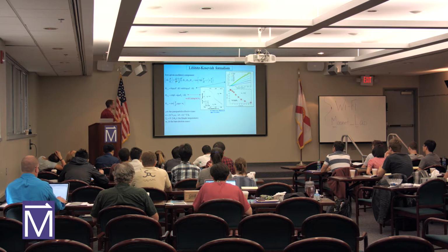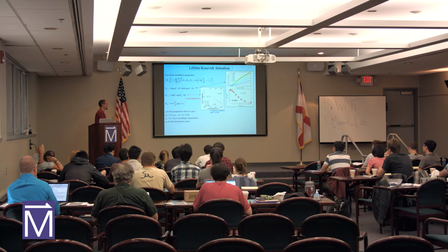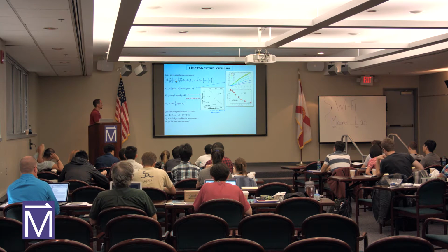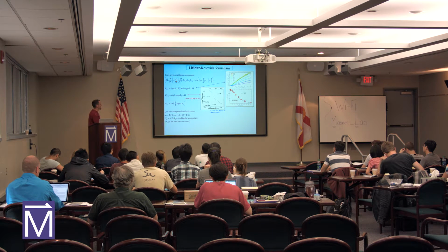And this talks about how the amplitude changes as a function of inverse magnetic field. Okay, so if you see the amplitude changing in a certain way, you can fit that. We already know the effective mass. Everything else is constants. And you can find the Dingle temperature of the material. That's usually a measurement of how clean the sample is, how easily the carriers are moving through the material. From that Dingle temperature, we can actually find the scattering rate and the mean free path through the material.